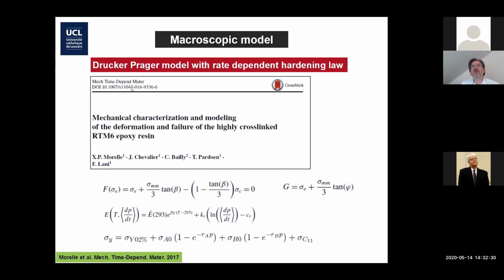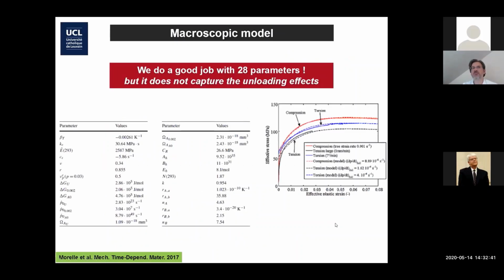So we decided to take a model with an intermediate level of complexity, to use Abaqus. We use Drucker-Prager with a rate-dependent hardening law. I'm skipping the details. 28 parameters. This is a typical cost for these types of models, where based on these 28 parameters, you can predict all different temperature, different rates, tension, compression, torsion, and a few more things. These are the 28 parameters.